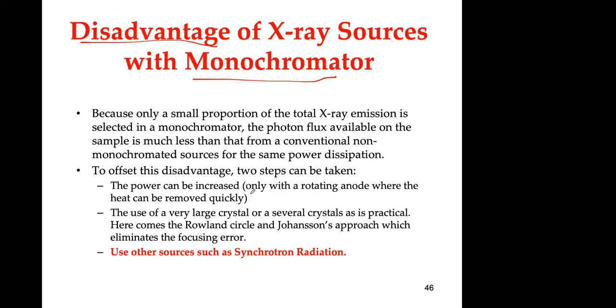They use rotating anodes, which is another way of doing it. They use the mosaic of crystals that I told you about, to enhance the number of photons that can go through the monochromator to hit your sample. And the other thing is to use a higher intensity source. You can use a synchrotron source, as you have at CHESS. So that's for the X-ray source.